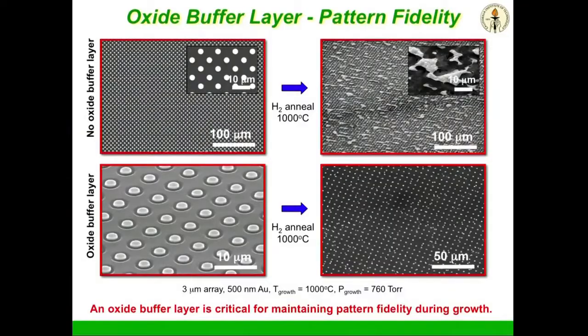And the way we fix that is if you don't like where your seeds in the farm are growing roots, you should put each one in its own pot. That's what we do. There's a silicon oxide layer. That silicon dioxide layer, we etch holes in it. We deposit the metal seeds in those sand pots, and it has nowhere to go, and so the pattern stays robust. In addition, we get smart about the depth of that pot, because we know the surface tension of the molten drop of that metal eutectic on the growing seed, and we make sure there's just enough metal for the diameter that we want to grow that it fully covers the diameter of the growing drop.